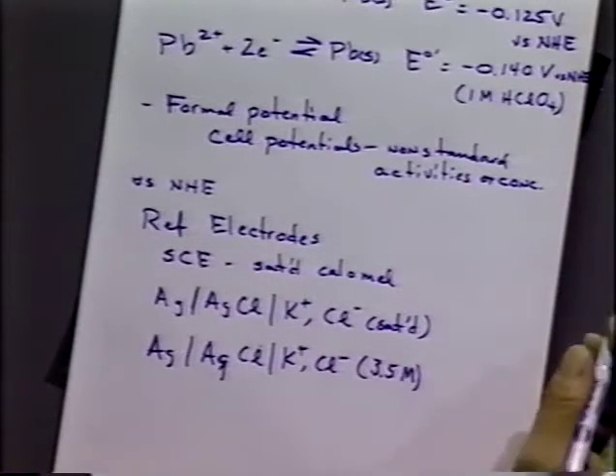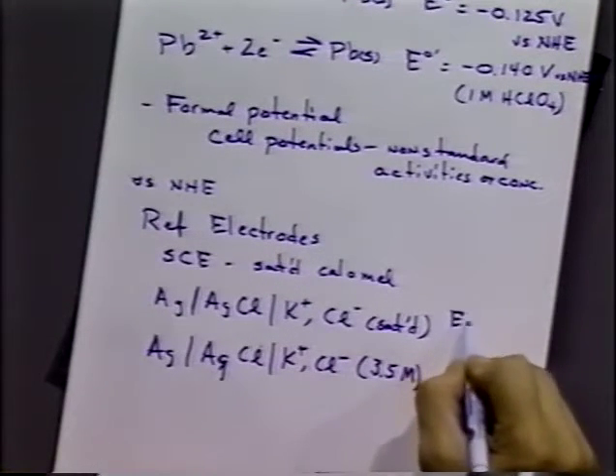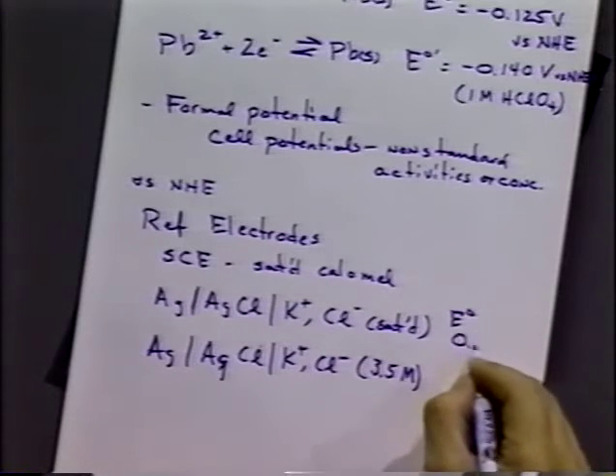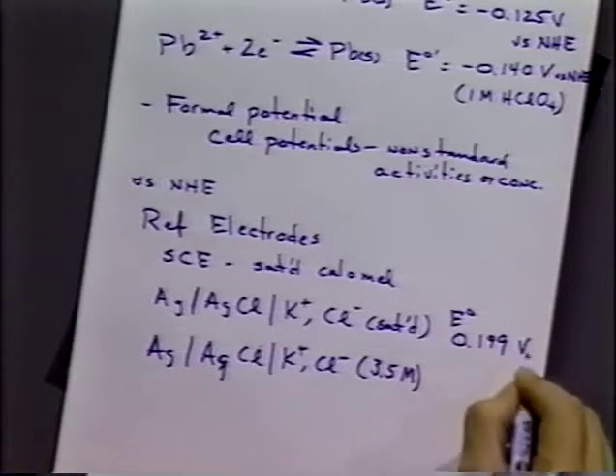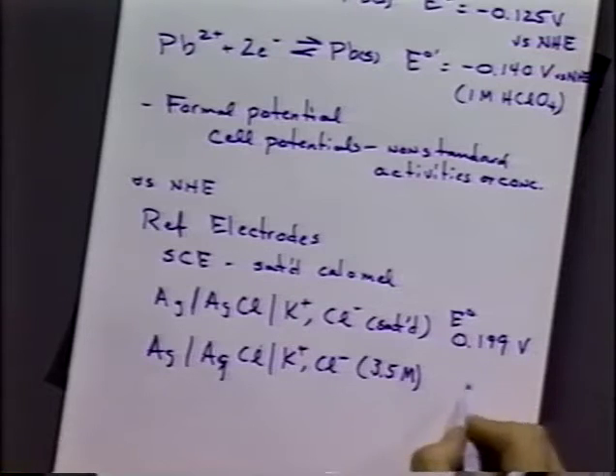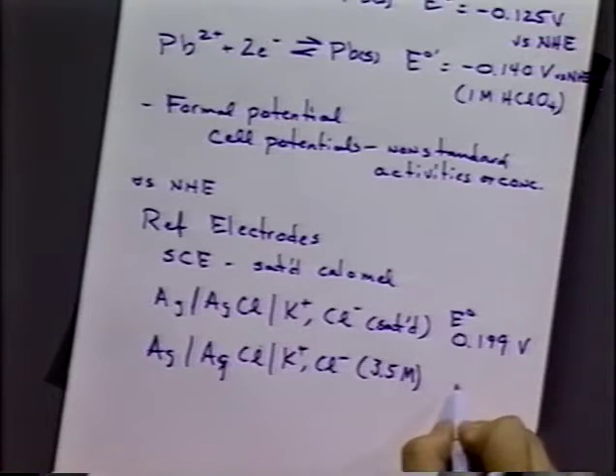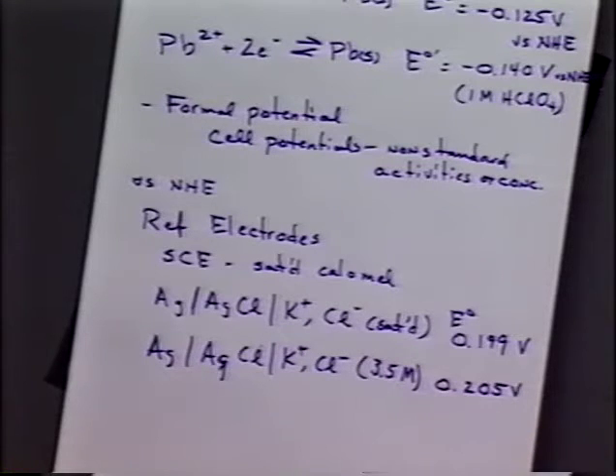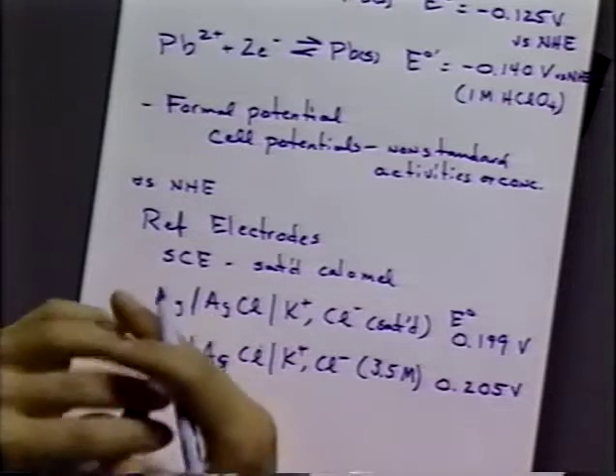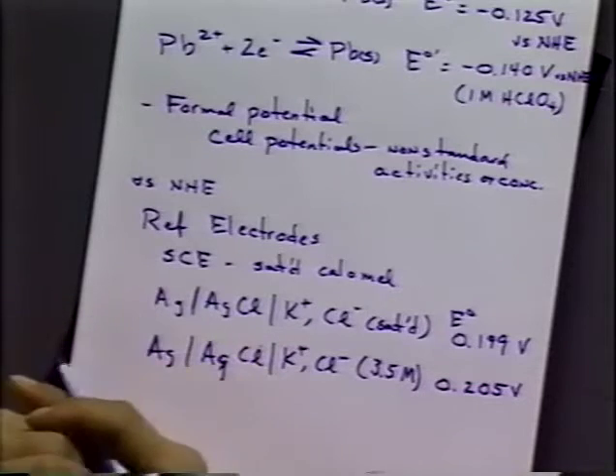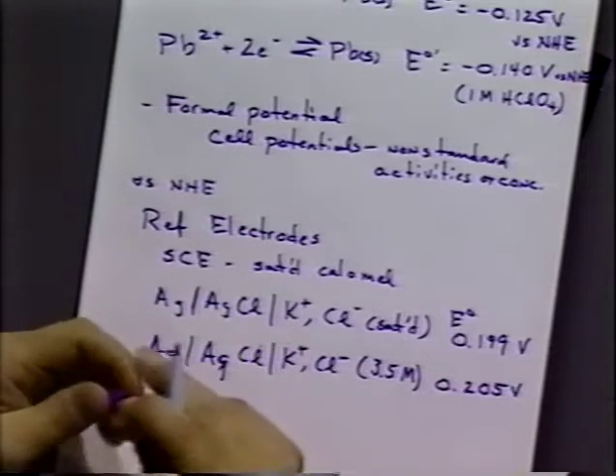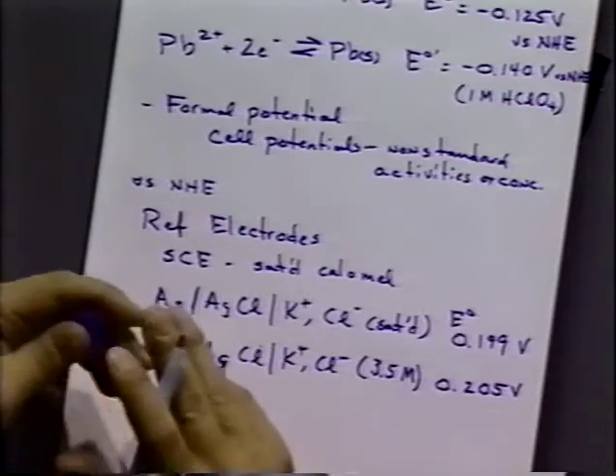Now both of those have very similar E0s, standard potentials, and that would be 0.199 volts, and these again are versus NHE. But this one with a 3.5 molar solution would be 0.205 volts. So you can see that difference in 3.5 molar KCl solution and the saturated solutions counts to about 6 millivolts of potential. Not a huge amount in analytical work, but in fact for precise potentiometric measurements, it's very important.